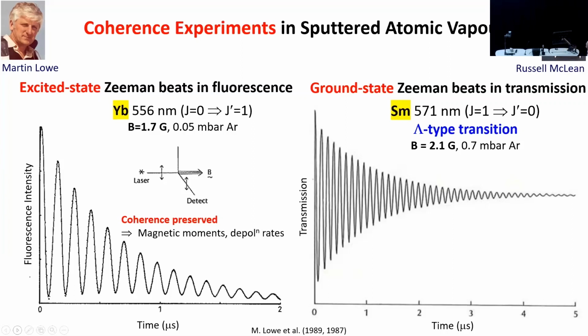And these are excited state quantum beats or Zeeman beats. We can also do ground state ones, and samarium has a very nice 1 to 0 transition, which is sort of a lambda transition where you can produce coherences in the ground state. And this is experimental data, this shows the beat pattern for ground state quantum beats, in which you can measure the magnetic moments and depolarization rates very precisely.